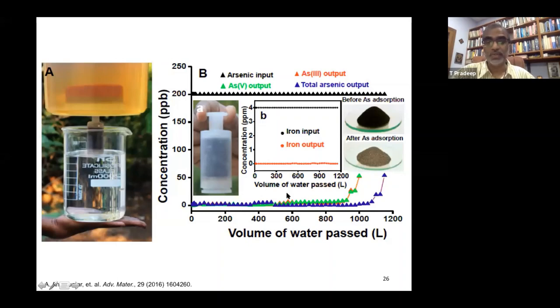As I told you, you run this experiment for whatever volume of water, and you find that about 1,200 liters of water can be cleaned with this. You not only put arsenic, you also put iron as well. So this is the iron concentration, 4 ppm of iron, 4,000 ppb, and this is what you get. The material to begin with is looking like that. Material after adsorption looks like that.